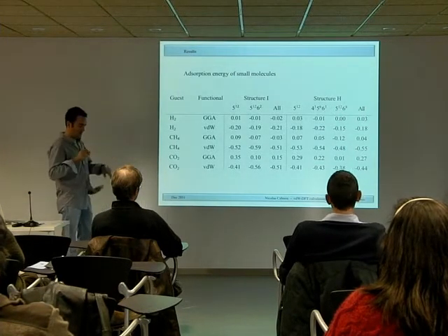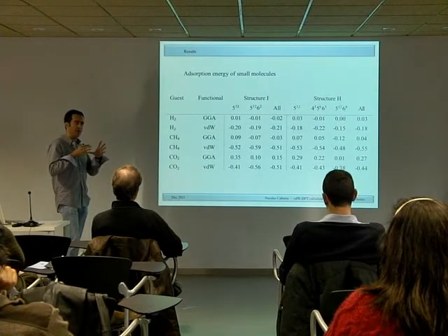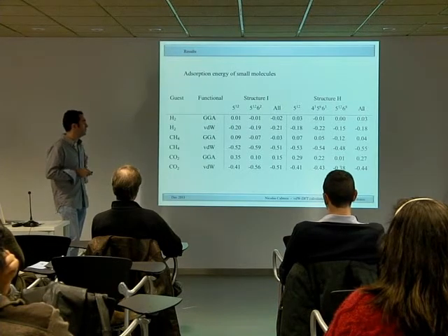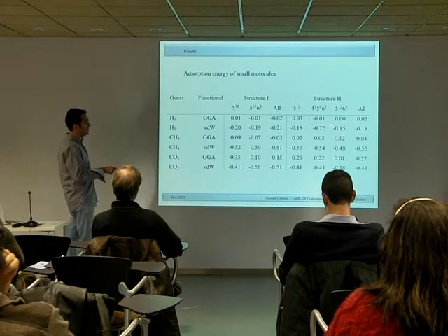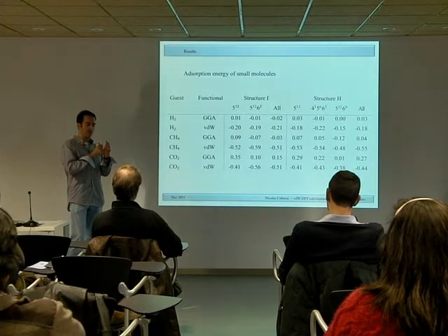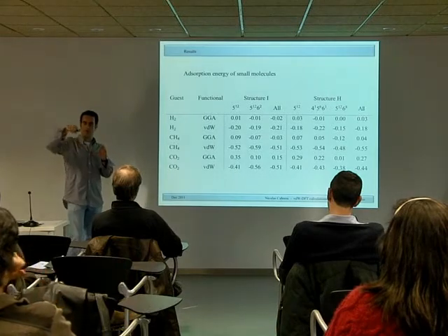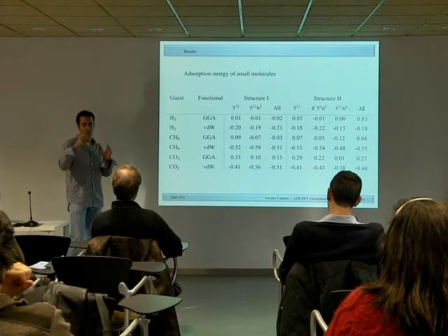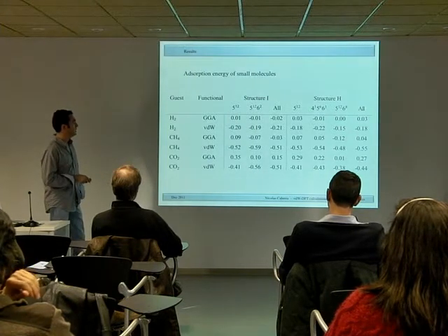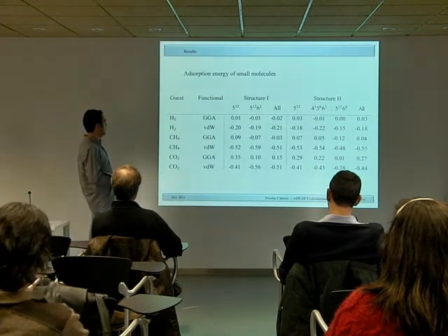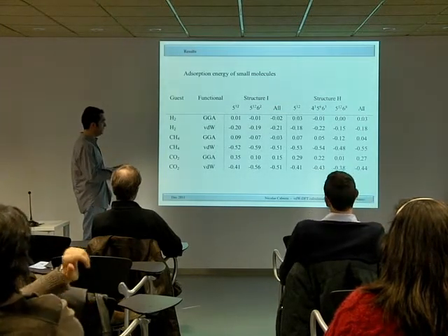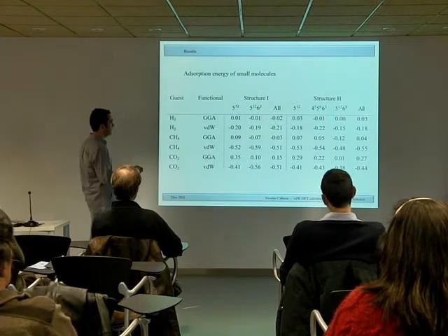This is because more or less all the cavities have the same radius, and all the molecules relax in the center of the cavities, except in this case where the molecule relaxes close to a wall, and that means the molecule doesn't interact with the rest of the cavity, or interacts less. That is the reason these numbers are slightly lower.